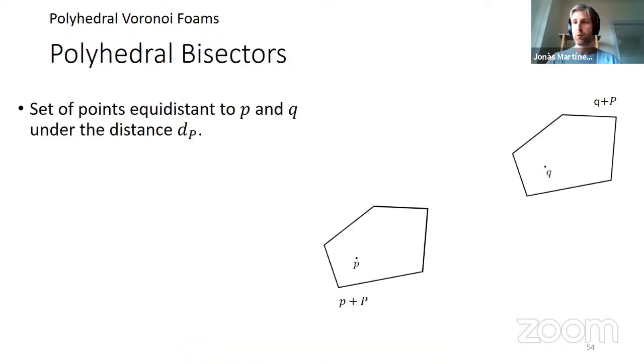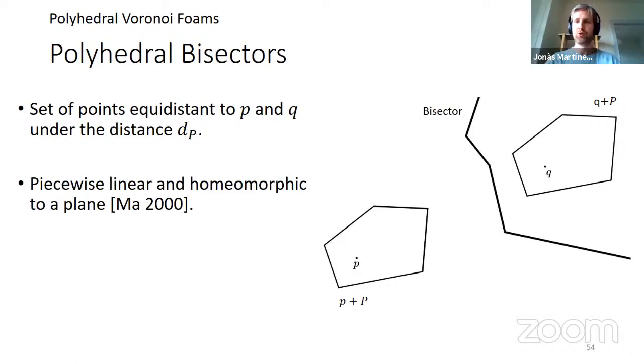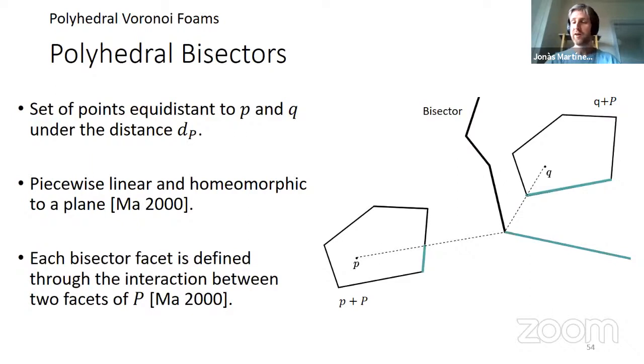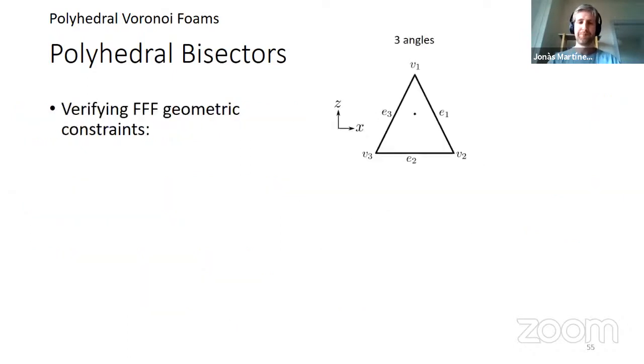So here, if you take this weird distance and you compute the bisector, you will get this bisector. And what we know from previous work is that this bisector is actually homeomorphic to a line in 2D or to a plane in 3D. So that's nice because it completely separates the two points. And what is very nice is that each facet of this bisector is actually defined through the interaction between two facets of your distance set. So here, for instance, you have this piece of a bisector that is defined by two parts.